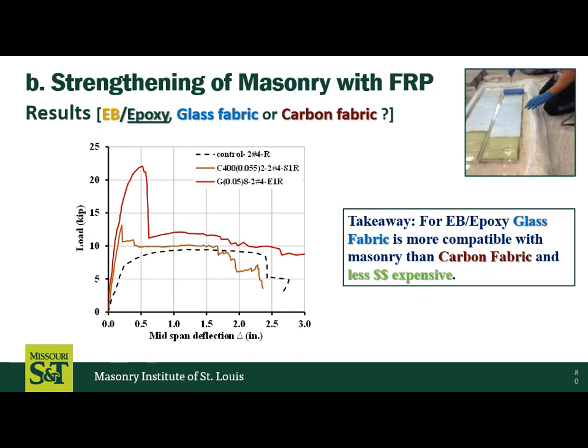You get a lot better performance out of the glass, even though the material has a lower strength or tensile capacity. And that's because of the compatibility of the two materials. If we think about carbon, very, very high strength, stiff, much stiffer than some of these other applications. And so from a compatibility standpoint, it actually makes more sense to use the lower strength, less expensive material when bonding to the surface. And the analogy I would use is if we look at concrete, and I'm batching up concrete here in Missouri, we use a lot of dolomitic limestone, right, as our aggregate source.